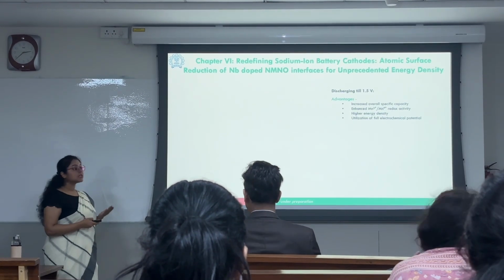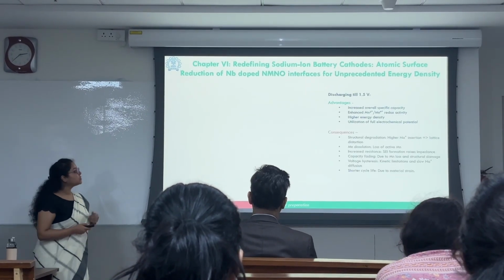However, there were certain consequences that we faced, which were the structural degradation, manganese dissolution, increased SEI, capacity fading, voltage hysteresis, and shorter cycle life.